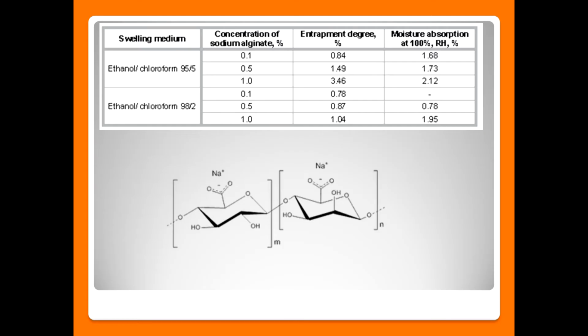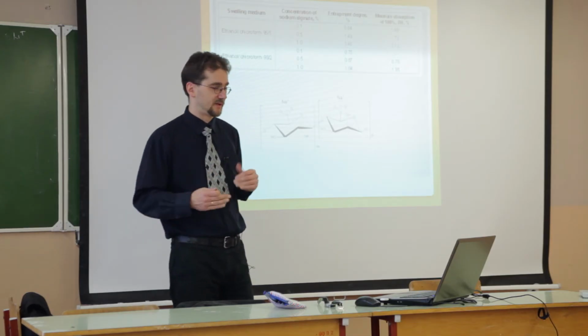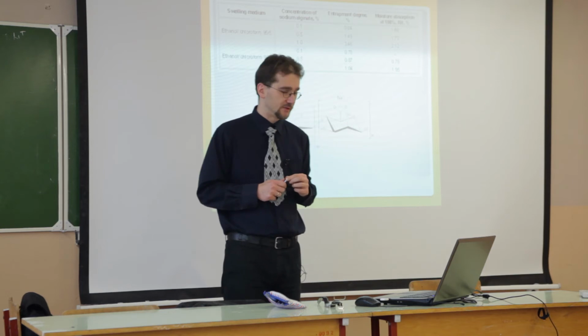Which properties can we change using surface modification? The easiest way to see changes in the structure is to control the moisture. The moisture absorption is different and depends on the amount of sodium alginate on the surface.